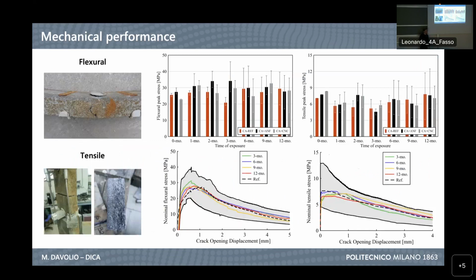From a mechanical point of view, we see some scattering of the results, which is even more significant than the evolution or any possible trend over time. This means that the specimens are not really affected by the condition they are facing, and they are, on the contrary, effectively healing and keeping their constant performance over time. So this is another confirmation of what we were trying to observe.